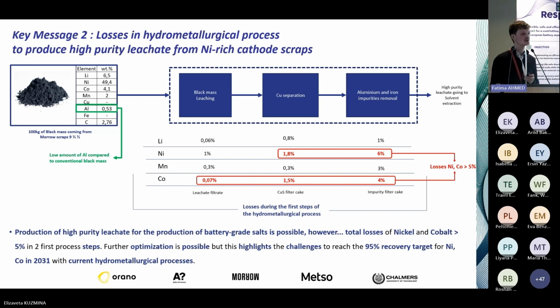So you also have here an idea of the composition of this black mass with low amount of impurities compared to standard black mass, only 0.5% of aluminum. What is interesting here is to see what are the different losses for the most interesting metals contained in the black mass at each of these process steps. And if we check for nickel and cobalt with this test, we have more than 5% of losses, around 7% for nickel and 5.5% for the cobalt. So with regard to the targets of the EU Battery Directive in 2031, with 95% of recovery for nickel and cobalt, for this test, we don't manage to reach this 95%.